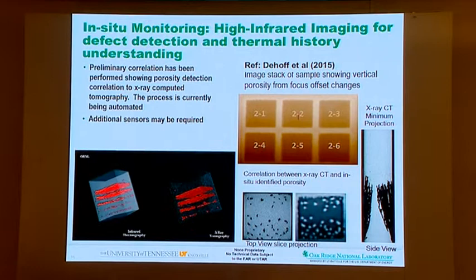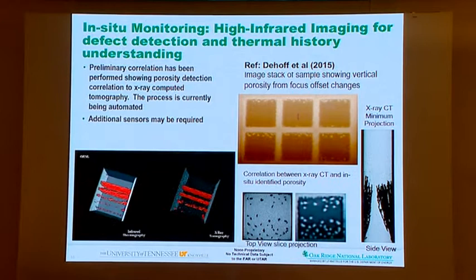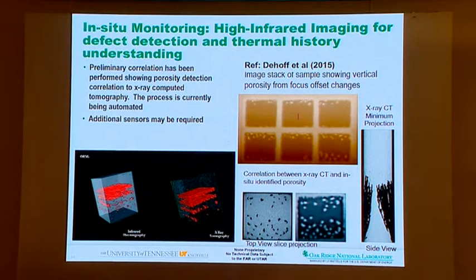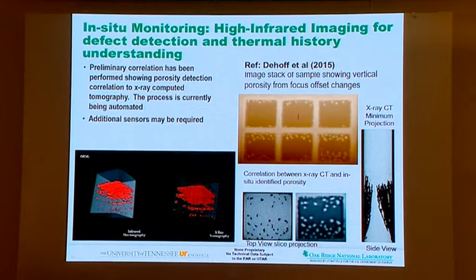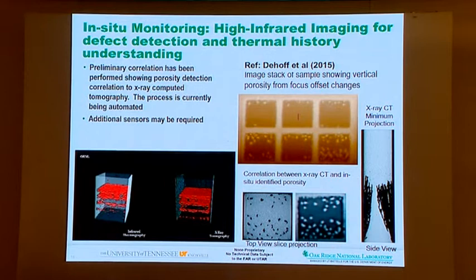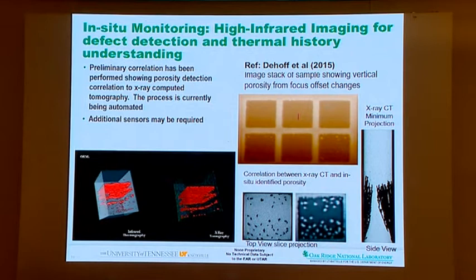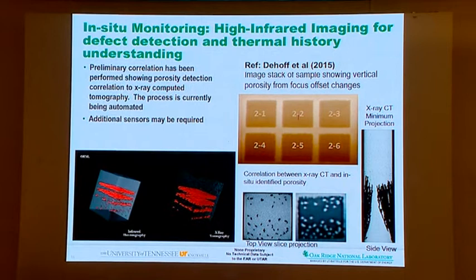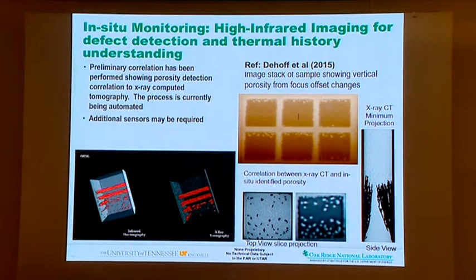Then we took the same sample and looked at it ex situ after processing, using tomography. You can do a one-to-one correlation, and then develop algorithms to figure out whether what I call a porosity during in situ imaging is actually going to end up as a porosity. You must ask the question, why are you worried about it? Let's say you're cooking one layer; if you put another layer, the defects could be healed by the time the n plus 1th layer comes. So we need to come up with algorithms to take care of that. With this information, my colleague Ryan Dehoff can now produce porosities anywhere in the build on demand.